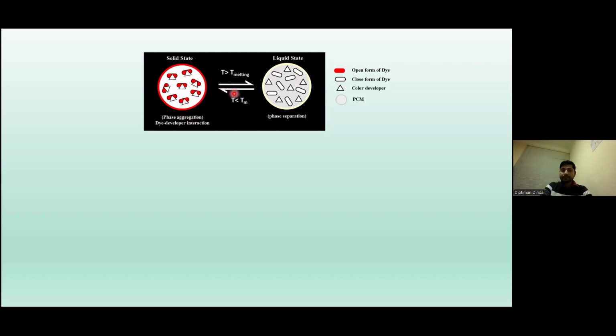When we melt those PCMs, then because of the better dispersibility, the color developer and dye will be dispersed in the liquid phase of the PCMs, and then there will be no interaction between the color developer and dyes. So now the closed form of the dye will be stabilized in the colorless state. So that's how we can design color to colorless thermochromic systems. Those are working reversibly. When we heat the mixture, it will be transformed to the colorless state, and when we cool down, it will turn back to the colored one.